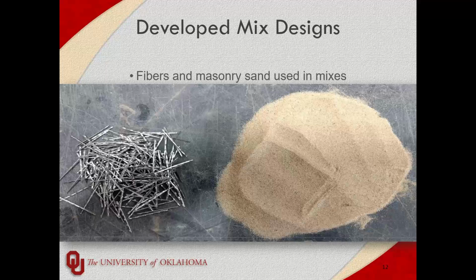But typical UHPC mixes will use a sand similar to this, but they will also use a quartz flour or something that's super fine. And we avoided using that mainly just for the expense, because those materials are very expensive, and it's best to avoid those if you're worried about cost. So next slide.